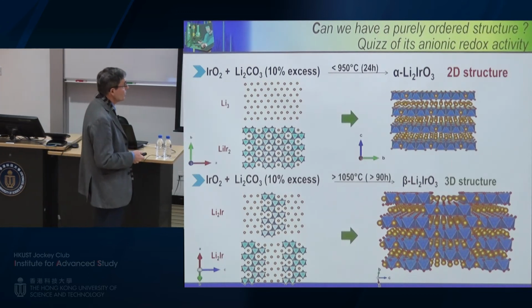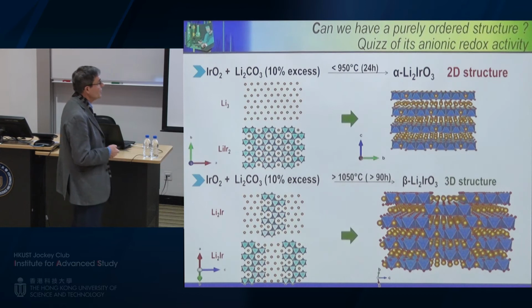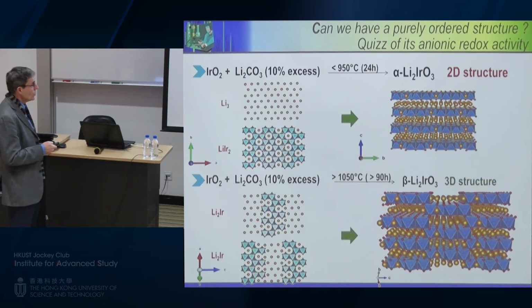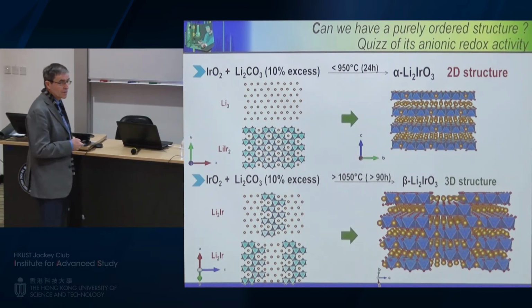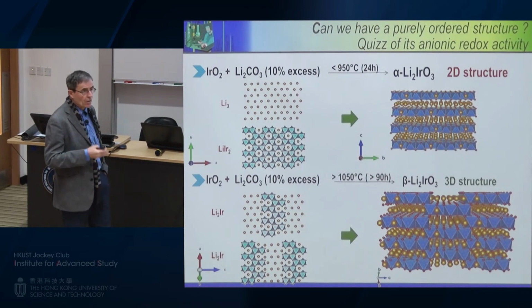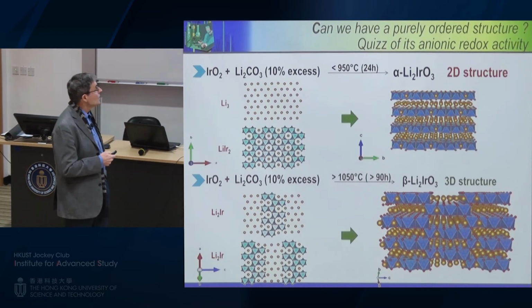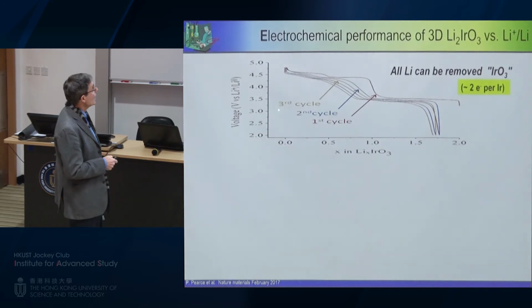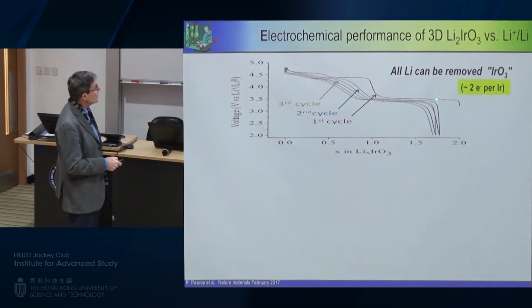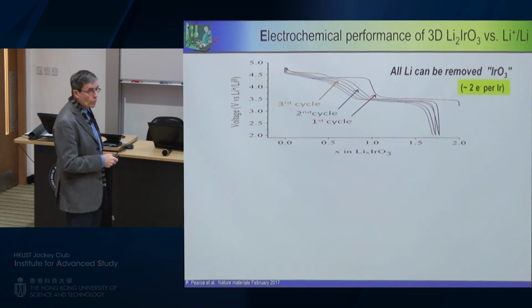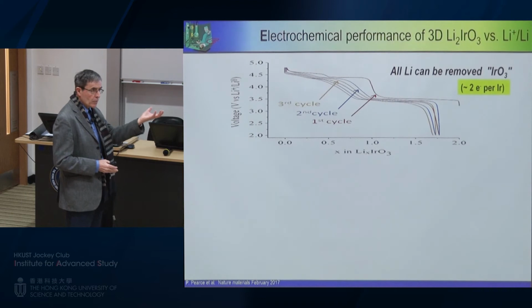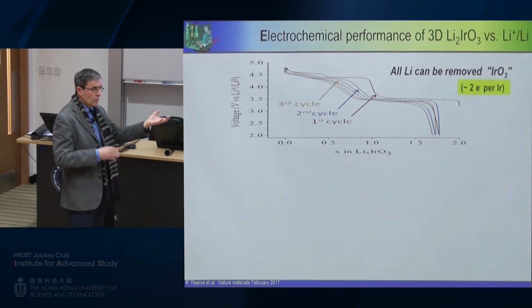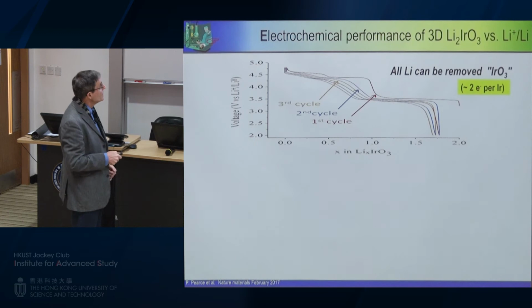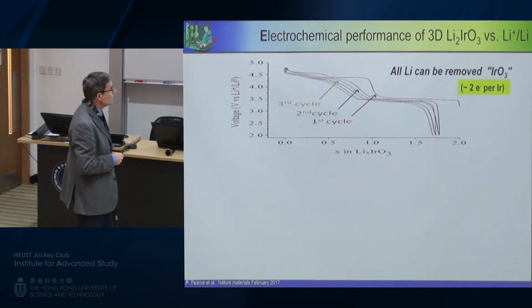And within this 3D structure, you can see now the lithium being in this channel and so on. So the question is, will this phase uptake or release lithium? The answer is here. Now you can see, we start at 2, and this time, we are able to remove all the lithium. Why? Because we have a three-dimensional structure, a very rigid framework, and when you remove lithium, you don't have any more gliding and so on, and this compound is very nicely reversible, and you remove 2 electrons per iridium.